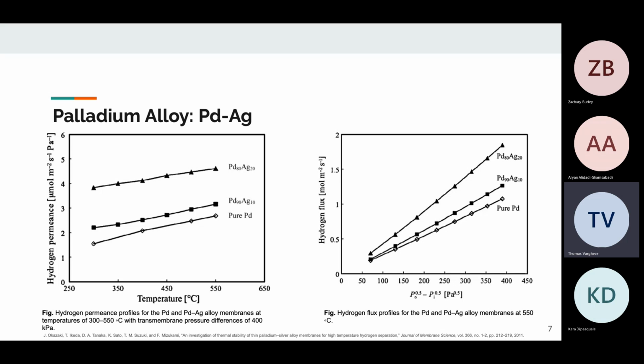The figure on the right shows hydrogen flux versus the pressure difference for palladium and palladium-silver alloy membranes at 550 degrees Celsius. It can be noted once again that the addition of silver to the membrane significantly enhanced the flux, which is seen increasing linearly with the square root of pressure.